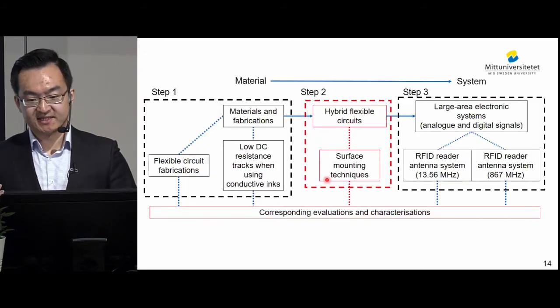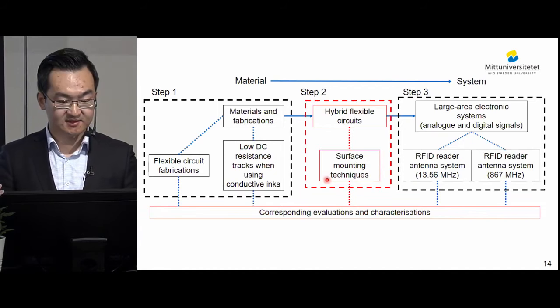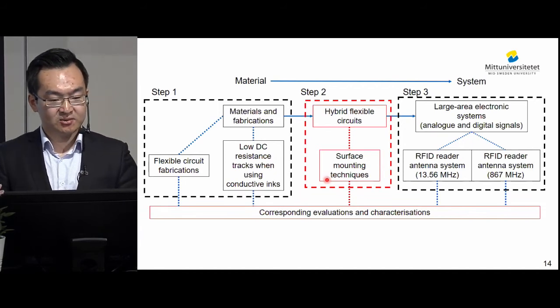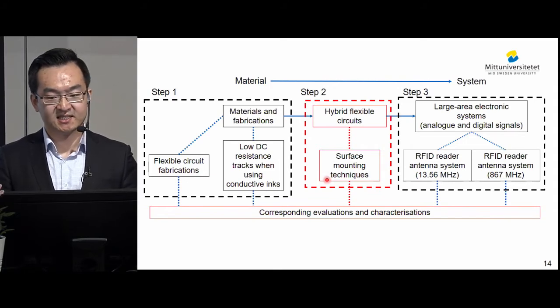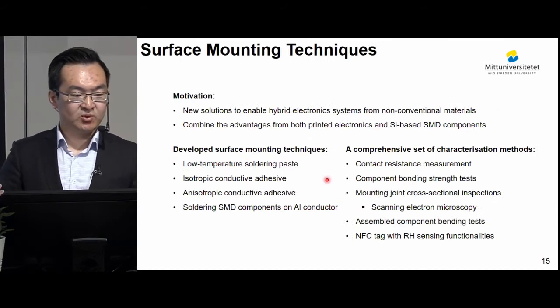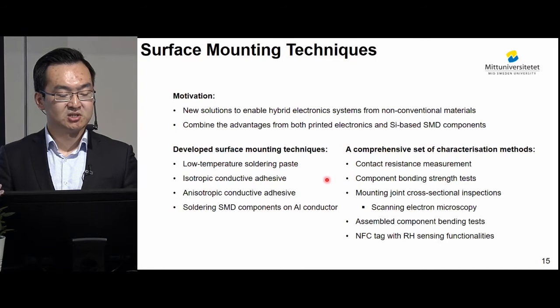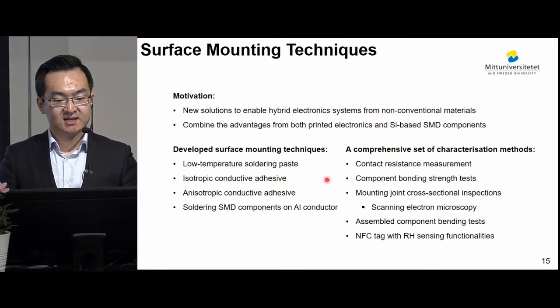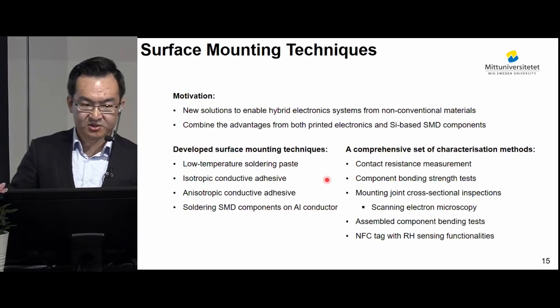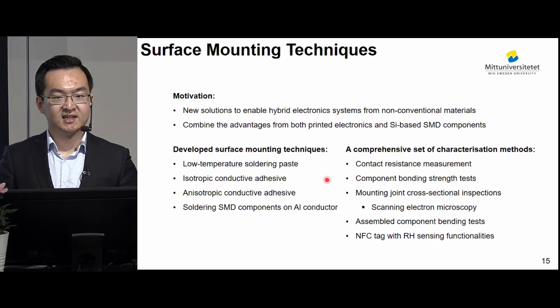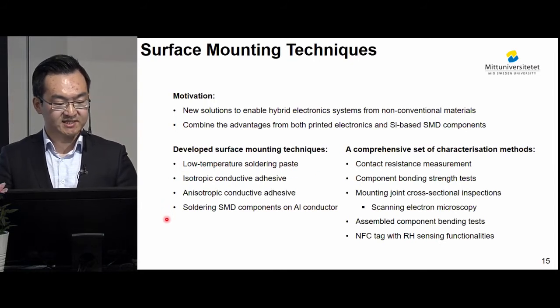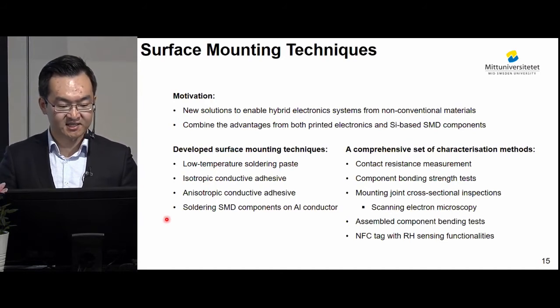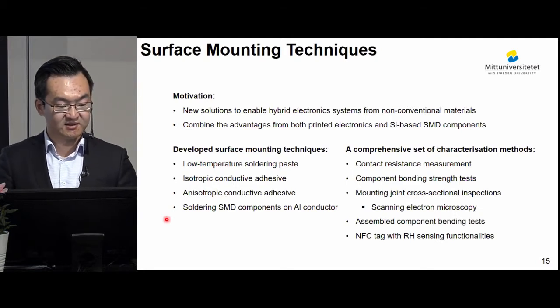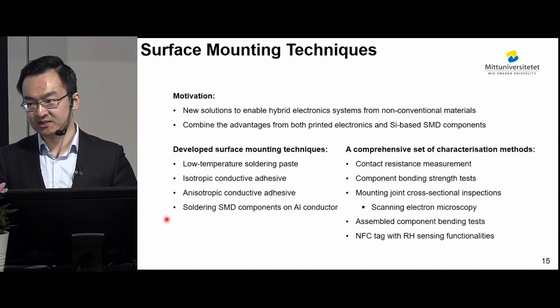Now, that was step 1 with the circuits fabricated. Now we move to step 2, where we will talk about surface mounting techniques. The reason why we developed surface mounting techniques is because we would like to bring new solutions to enable hybrid electronic systems made from non-conventional materials. In that case, we could combine the advantages from both printed electronics and the silicon-based SMD components. And we have developed the following 4 surface mounting techniques in this thesis work: using low-temperature soldering paste, isotropic conductive adhesive, anisotropic conductive adhesive, and a special method to mount components onto aluminum conductor.